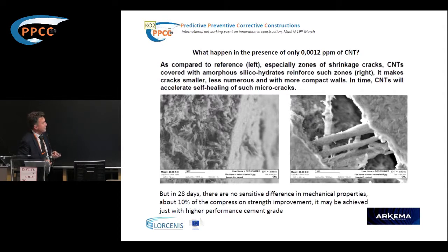If you look at scientific articles, you can find different works explaining the mechanism of how this happens. For us, the interest is in taking advantage of this effect. What happens in factory testing is that in 28 days, samples are measured for compression strength and bending properties to judge the efficiency of additives. In our case, the advantage is probably around ten percent — not enough to attract strong interest from construction companies or factories, since simply increasing cement quantity or adjusting the formulation achieves the same result.